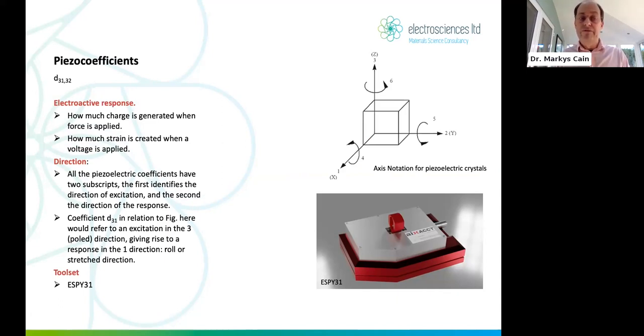But the d33 and d31, this is where you're applying a force in one direction and measuring the charge in the opposite direction, in an orthogonal direction, like you would do for stretched PVDF polymer. You'd pull it and you'd have electrodes top and bottom of the sheet, and that's this direction, so they're orthogonal. And this is a 3-1 or a 3-2 if you stretch it in the other direction. And yeah, we have a tool for that as well from Electrosciences, which you can see in the bottom right.